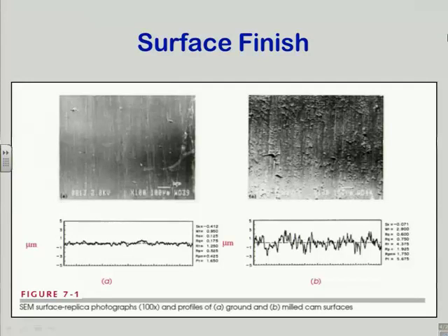Now, the track you see below is a measurement of the roughness of that surface done with a very fancy machine called a profilometer. And this was done probably 25 years ago. Profilometers now are often lasers that don't even touch the surface, but this is a contact profilometer. It has a diamond stylus. If any of you are into hi-fi and still use records, it's much like a cartridge that's used to track a record groove. And it has a radius on the tip of the diamond of about a micron. So that actually serves as a filter because it can't detect anything smaller than that radius. So you'll never see anything smaller than that.